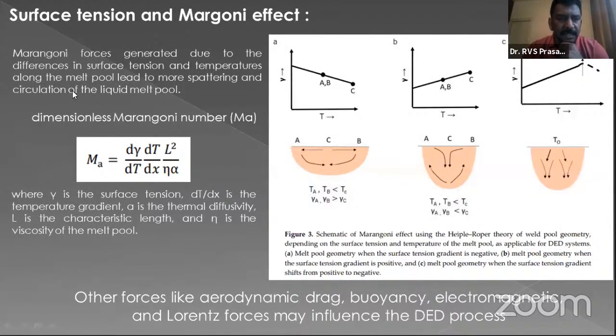So you consider the dimensionless Marangoni number, which can be determined by M equals ∂γ/∂T, ∂T/∂x, and L squared, divided by η α. A lot of things come into the picture here, which are very critical for this particular DED. Here γ is the surface tension, ∂T/∂x is the temperature gradient, α is the thermal diffusivity, L is the characteristic length, and η is the viscosity of the melt pool. So all these physical properties will determine your melt pool dynamics.